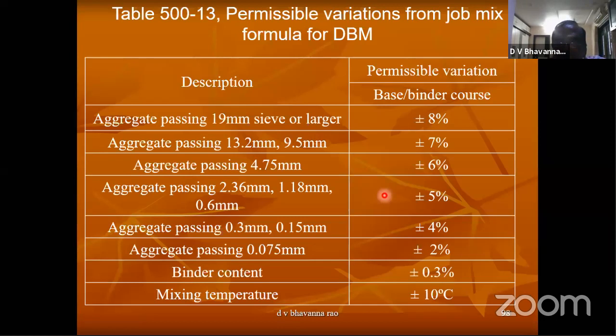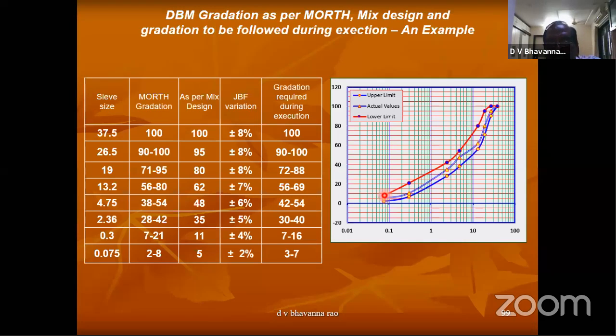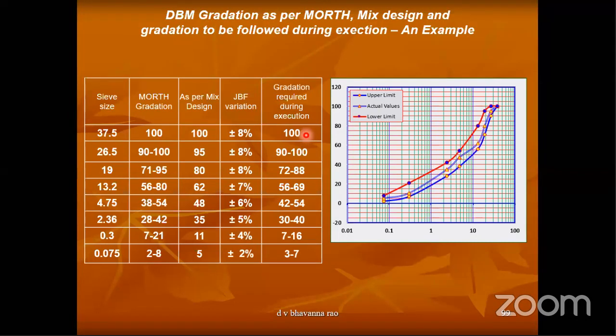These are the job mix formula at the time of design. I have shown some example of this gradation. This chart shows the outer lines of the gradation and the inner line. For one DBM sample, I am showing this one. On 37.5 mm sieve, 100% is to be passed and 100% is passed. The allowable variation on this sieve is plus or minus 8%. But we should not change 100%. That side is 100%.